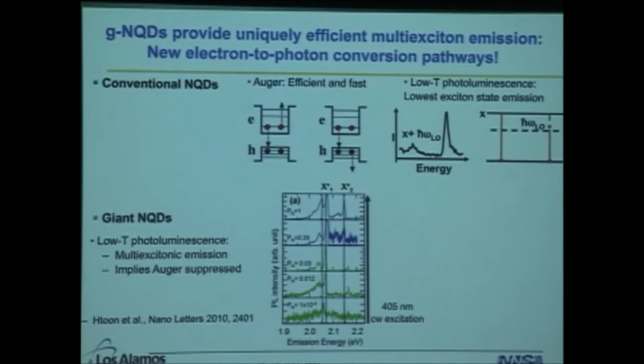He uses a low temperature photoluminescence method, and what he sees is that when you pump a conventional quantum dot very, very hard, as you're increasing the pump intensity, the pump fluence, your intensity increases, but only to a point. And then those quantum dots will photobleach and die and never come back, and you've destroyed them. And also, you only see a single emission peak, and maybe it's LO phonon replica over here, even at high pump intensities. Whereas in the case of giant quantum dots, as you keep increasing the pump fluence, you start introducing new states that are emitting.